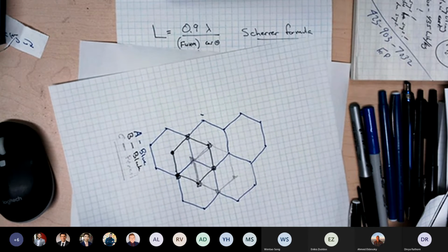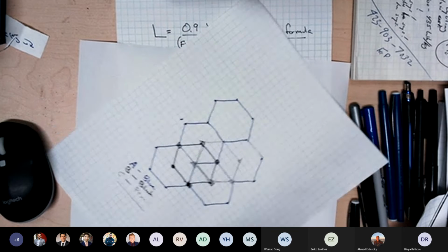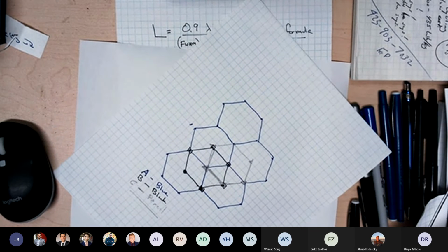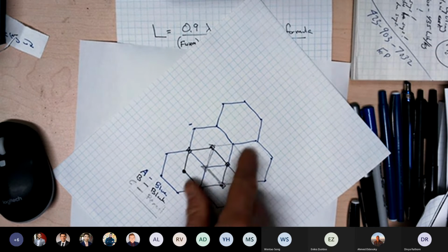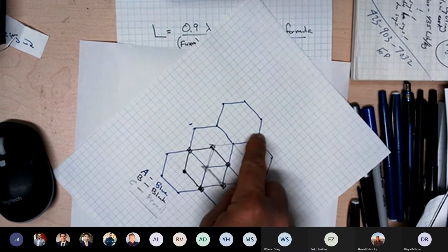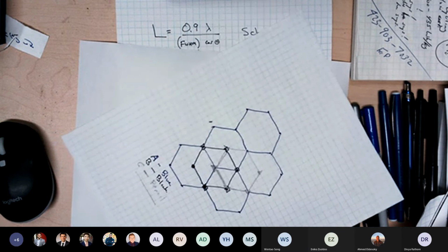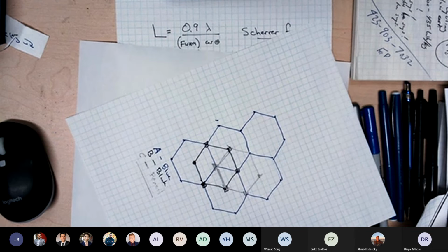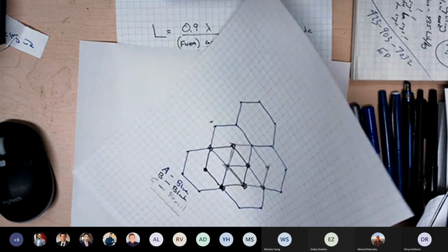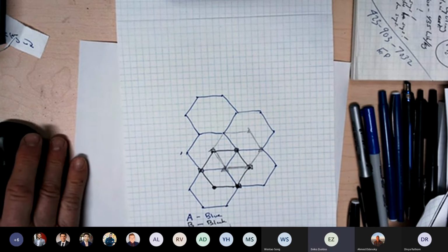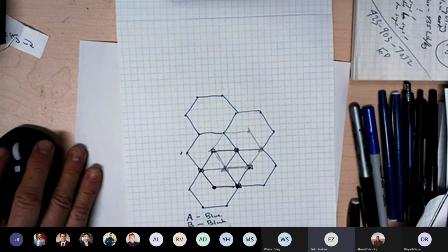So we don't know what the angle of rotation is. And for this structure, every 60-degree rotation takes you back to where you were because it's a 6-fold symmetry of the graphene sheet. So the worst possible arrangement would be a 30-degree rotation, not a 90. Well, a 90 would be equivalent to a 30, actually. Right, I see. That makes sense. Okay. Yeah. Thank you.